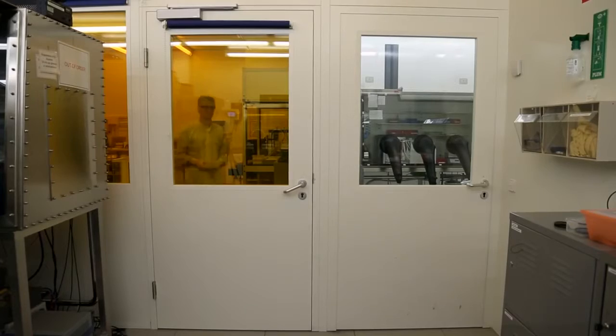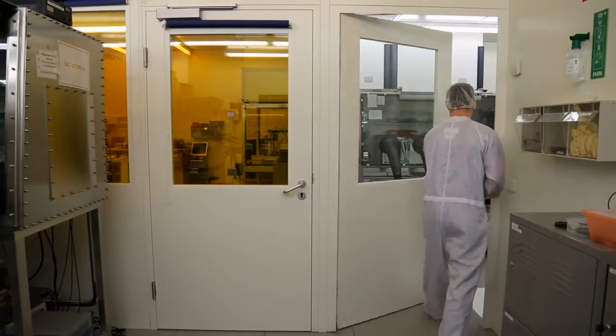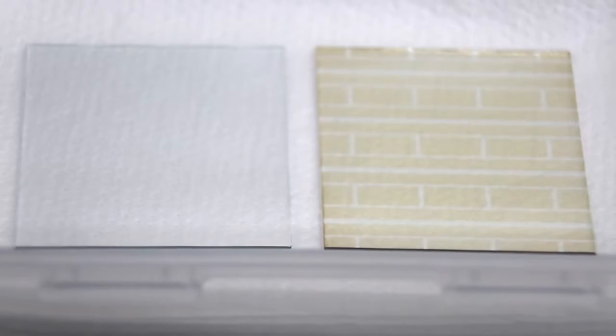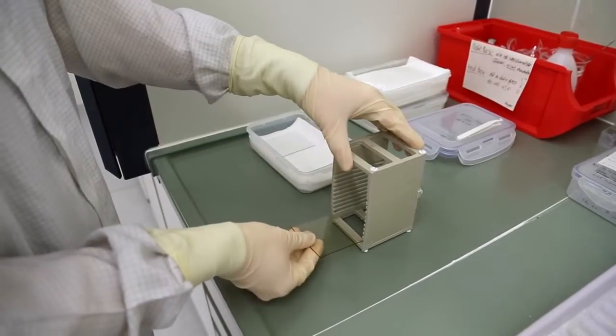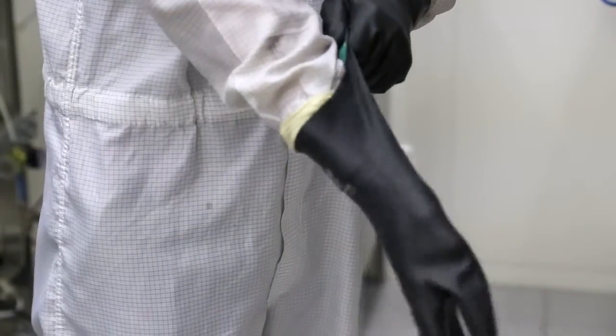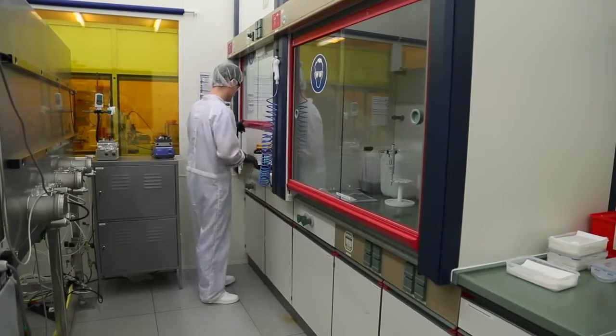Scientist Daniel Baru demonstrates the manufacturing process of an organic solar cell. OLEDs can be manufactured in an analogous manner. The starting point is the anode — a coating consisting of indium tin oxide, abbreviated as ITO, deposited on a glass plate. The ITO is coated with a light-sensitive photoresist, which is developed only at the locations that are to be etched. The remaining parts will conduct the electricity later on, similar to manufacturing a printed circuit board.